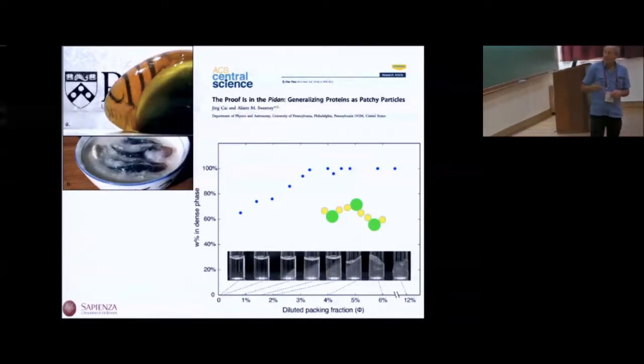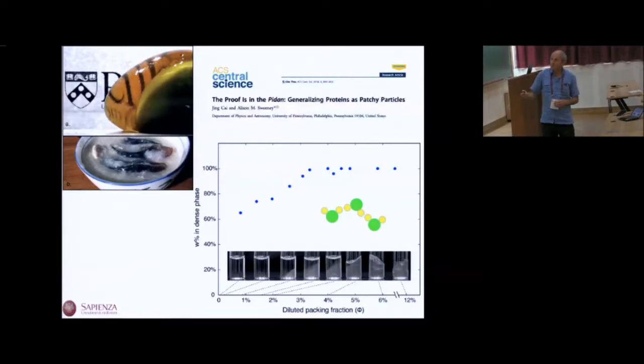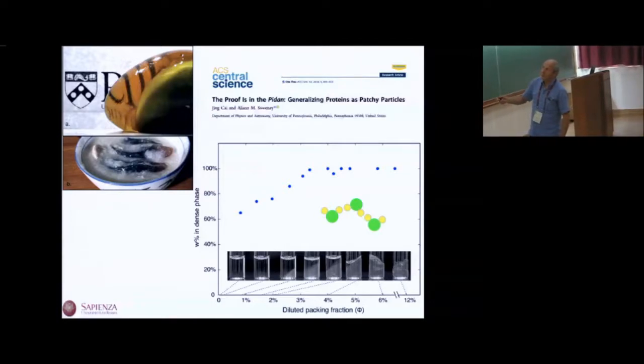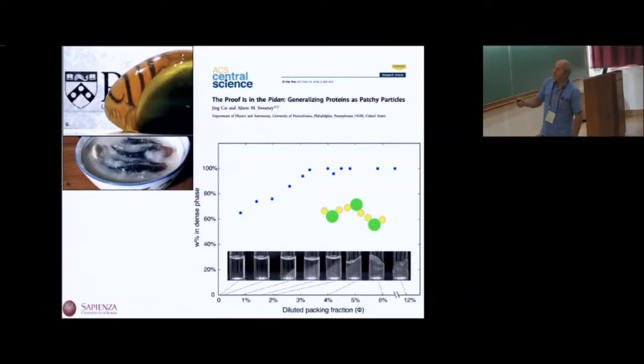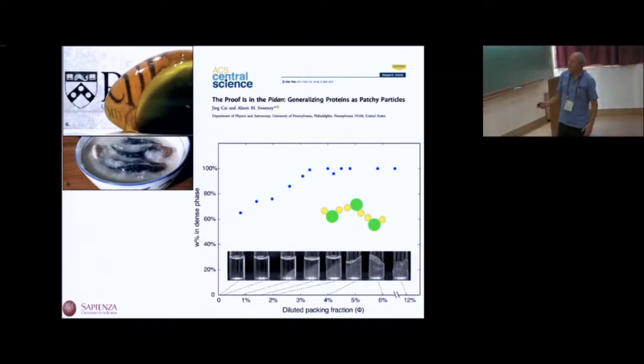This is the Pidan. This is the century egg that people eat in China. Those eggs, they keep the eggs for a very long time until they form this gel. It is due to some chemical that enters in the egg. And this is how they look in a Chinese restaurant. And these gels that they form in this century egg are also similar. You see a phase separation process of very low density, less than 10% in packing fraction. There's a coexistence between these two phases. And again, if you plot the data, you show that there's a real physical separation between two different phases. And again, such a low value of density in equilibrium can only indicate limited valence systems.